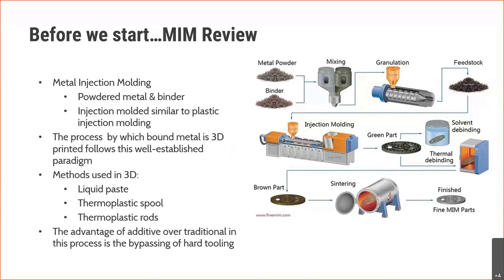So the first half of the MIM process actually mimics that of the injection molding process. But instead of using a thermoplastic, we use metal powder, and that metal powder is held together with a binder. We take that metal powder and combine it with the binder, and that material is what's called feedstock. You can think of the feedstock as being your thermoplastic that you would inject into your mold cavity. Once your part is formed, you have what's called a green part.